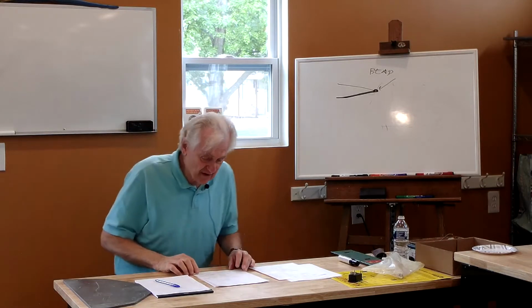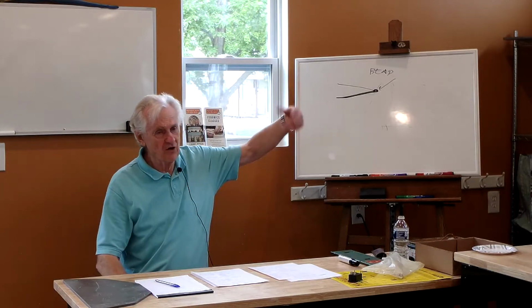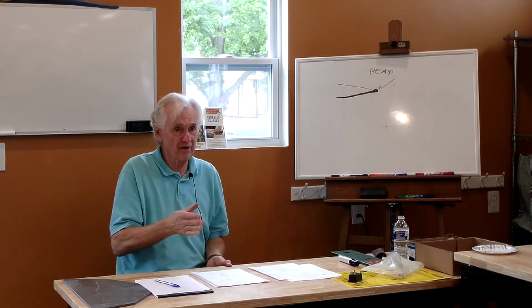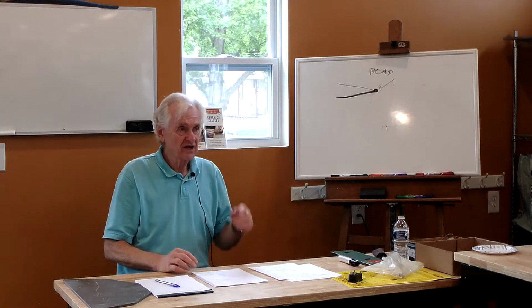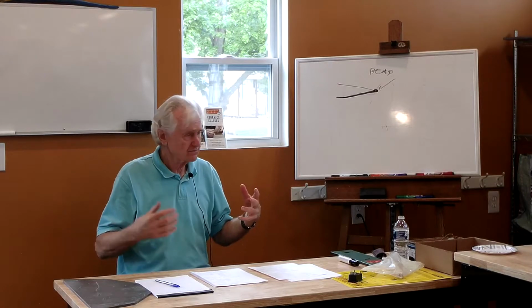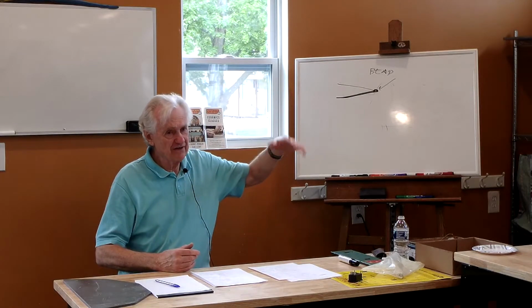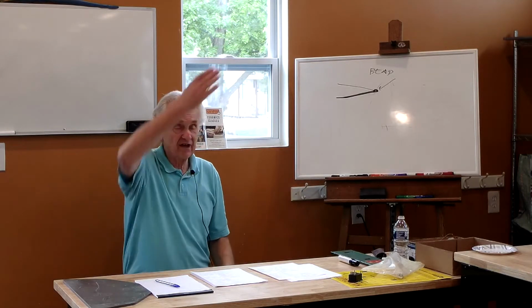Now, what's interesting about this is that if I say cone 6 medium, there's nothing standard about that, by the way. Medium might depend on the kiln company. What one company thinks is medium might be fast for another company, so you have to find out. But we talked about how we fire by heat work. What the company has done is worked out, for that particular size kiln, if I put this amount of power into the elements for 2 hours, essentially how much heat work they're getting, and that's how they've worked out the schedules.